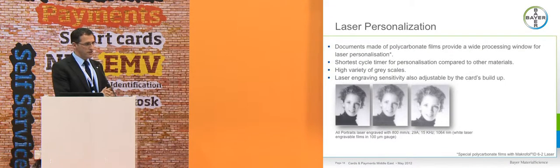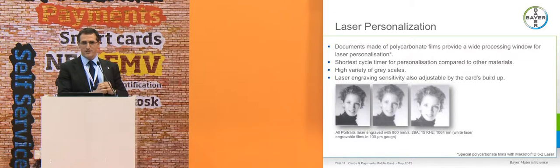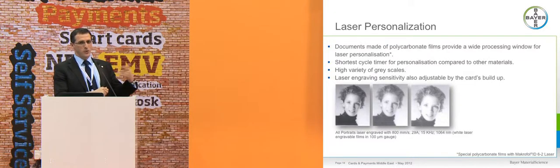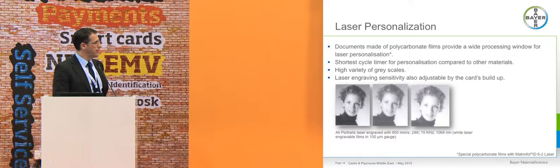Laser personalization. Something that most people don't know: polycarbonate is actually not laser engravable itself. We make the films laser engravable by putting special additives into the polycarbonate resin. And by doing that, it's possible to get very good laser engraving results, as you can see here.